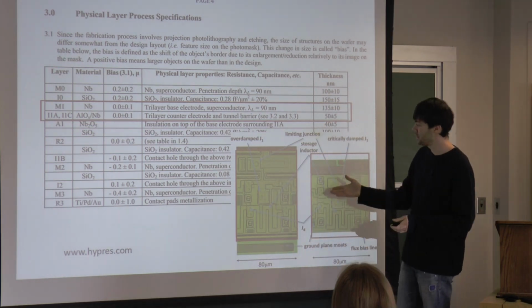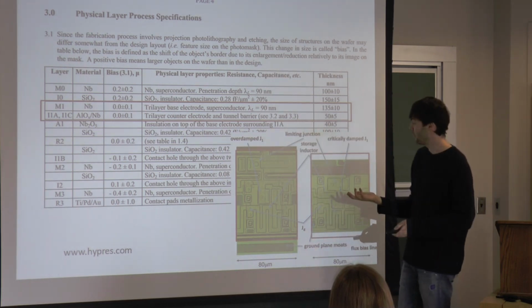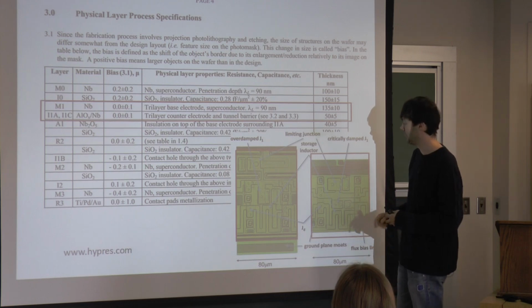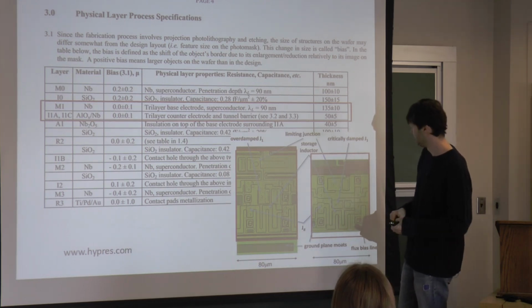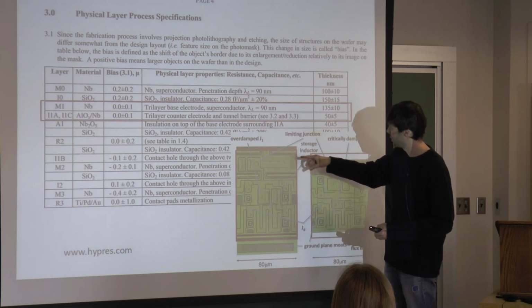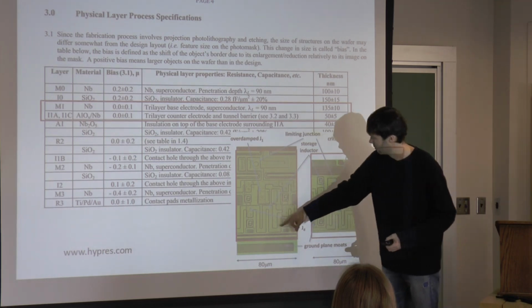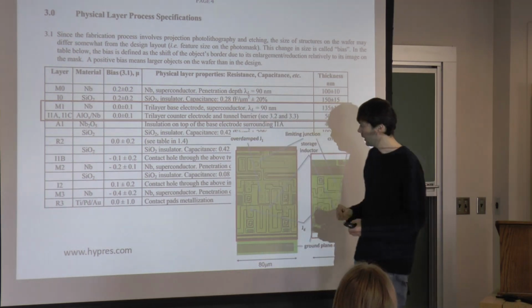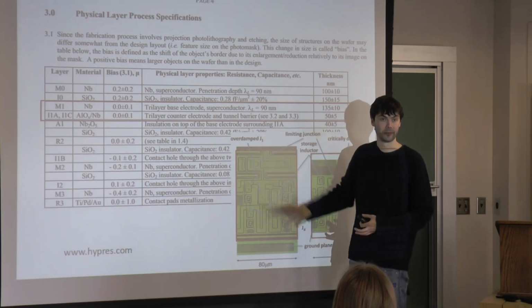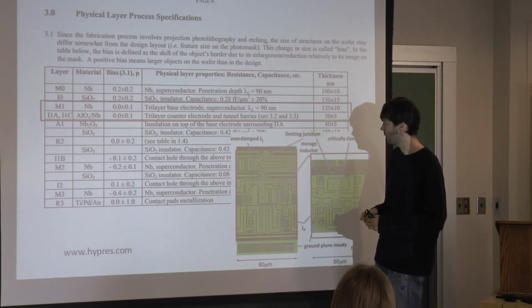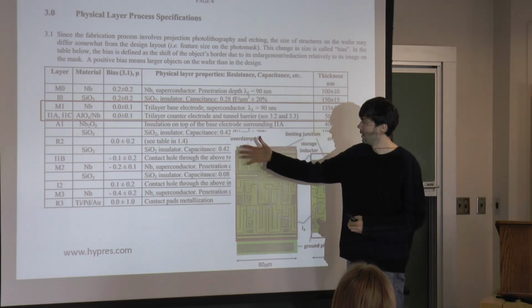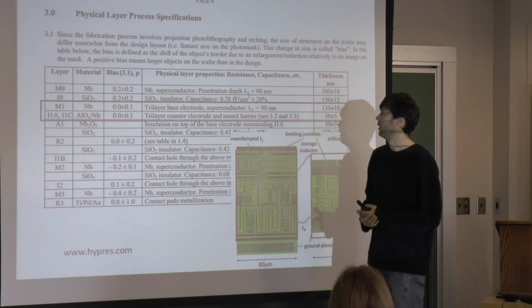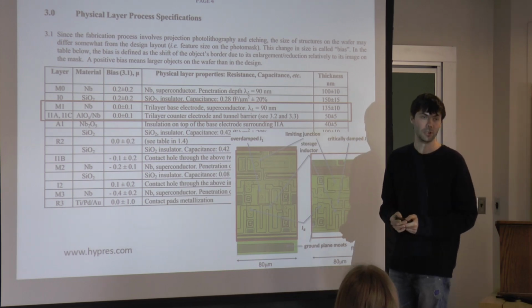This is an example of such circuits. Here the analogy to integrated circuits is quite applicable, because this is also a computing circuit where classical, not quantum, logic operations are done with magnetic fields created in the loops of Josephson junctions. So here are a bunch of different Josephson junctions. Some are bigger, some are smaller. Other elements include inductors. And the reason why you have so many layers in addition to this important one is because you want to connect different junctions with superconducting interconnects, and also maybe create shunt resistors, etc. So some of these are shunt resistor layers, some are interconnects, and some are dielectrics to separate different layers. So this is a very highly controlled technology, niobium Josephson junctions.